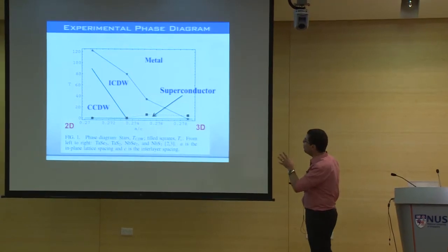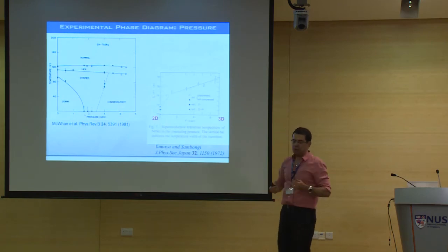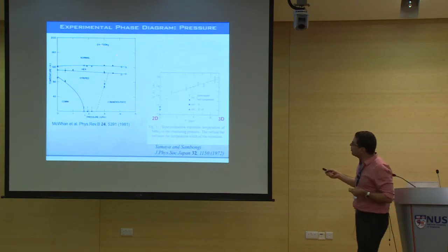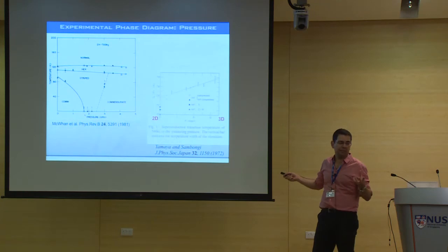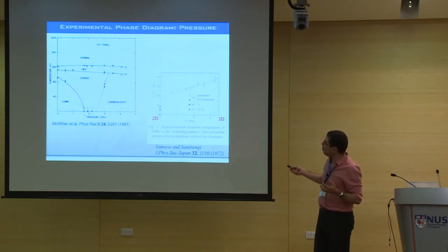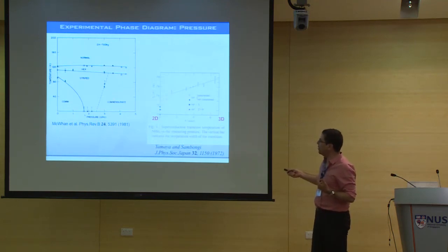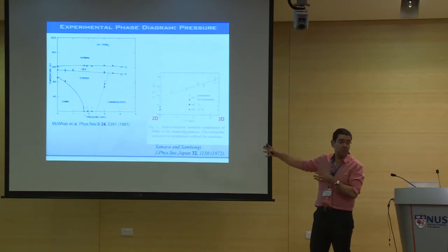So this is one phase diagram. Another very interesting phase diagram is this one, 1981, pressure. So you can apply hydrostatic pressure. And what's seen in this is tantalum diselenide. You see lots of different geometric phases. Okay, this has to do with this charge density wave. So this charge density wave will go from a normal metal to a hexagonal phase to a striped phase to a commensurate, in two different types of commensurate phases with pressure. Okay, this is a lot going on in a single material.